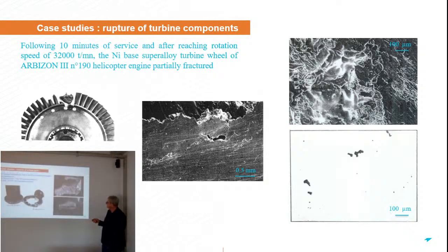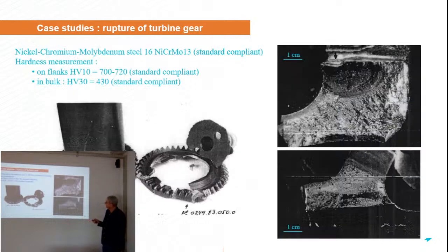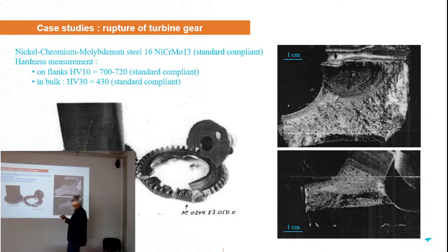Another example here, where you get the material, a nickel chromium molybdenum steel, this grade, which is okay in terms of standard compliance, and on which we did hardness measurements. On the flanks, we got about 700 to 720 Vickers, which is okay.